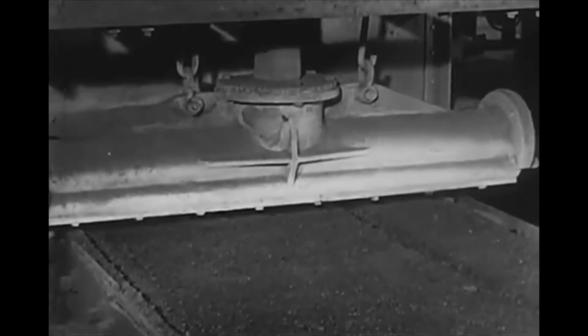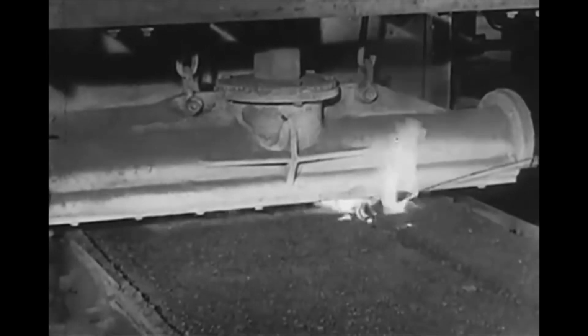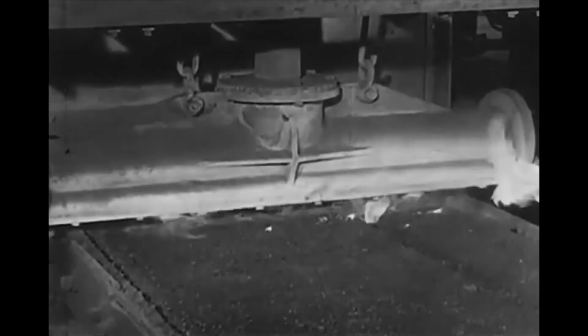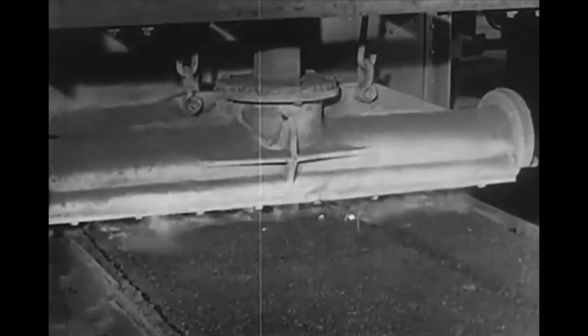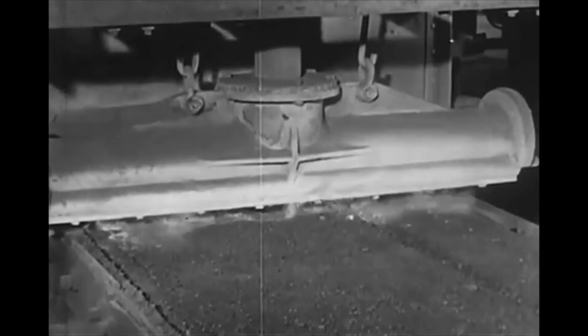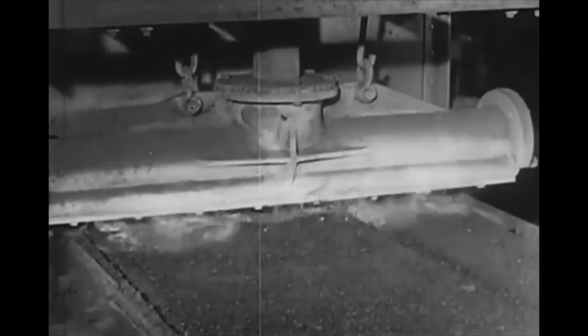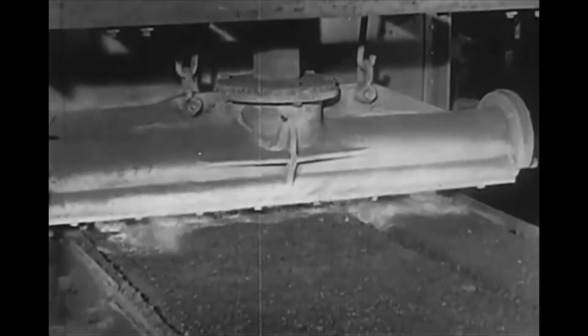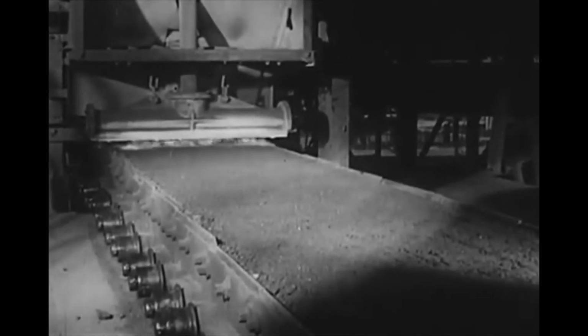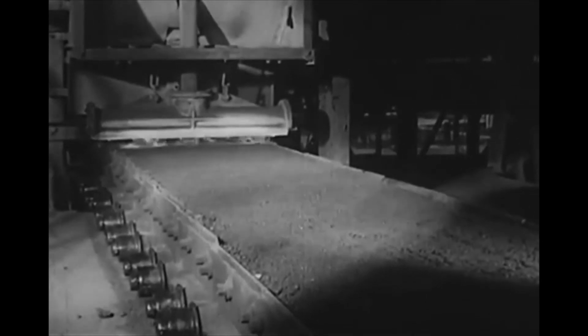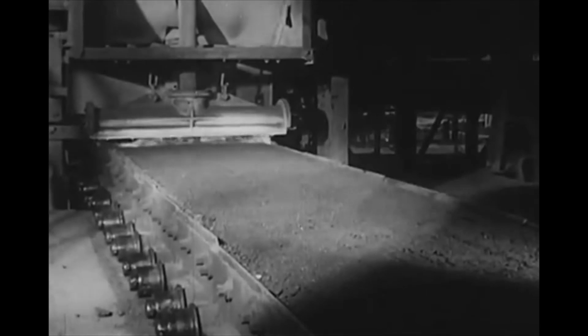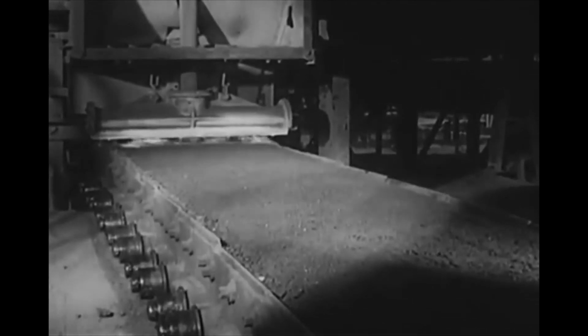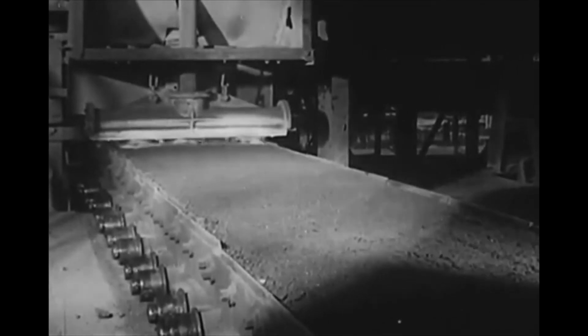Pallets carry the mix under gas-fired burners. During this slow process, ignition takes place from above. Suction fans create the necessary draft in a downward direction through the pallets of sinter mix. The method of igniting the mix may be likened to a man lighting his pipe and drawing air through to keep the tobacco burning. The smoke and fumes pass downward through the pipe bowl.